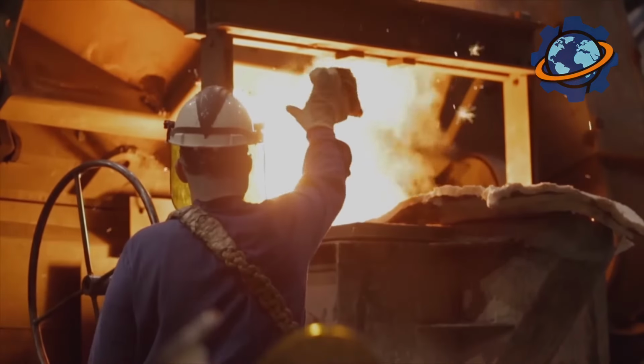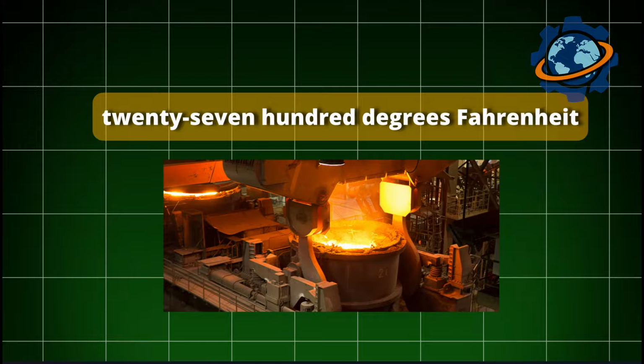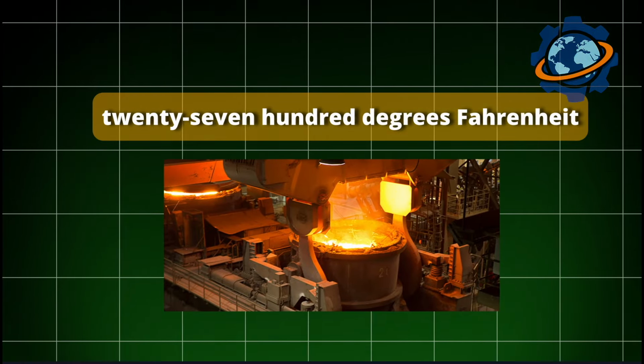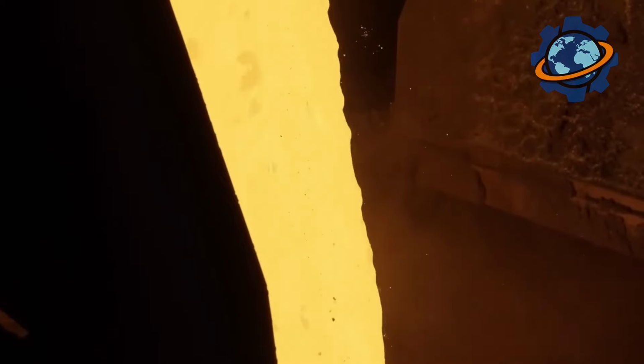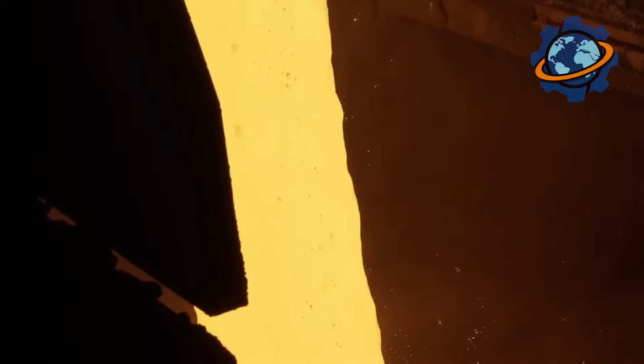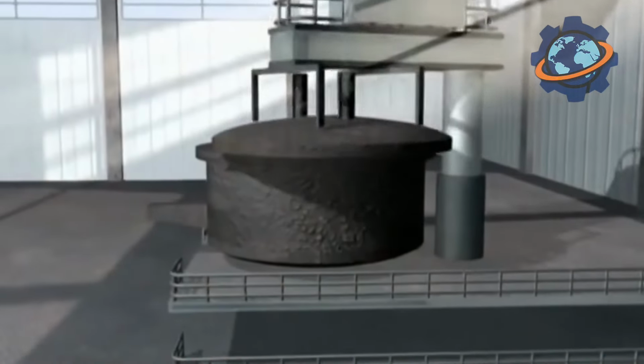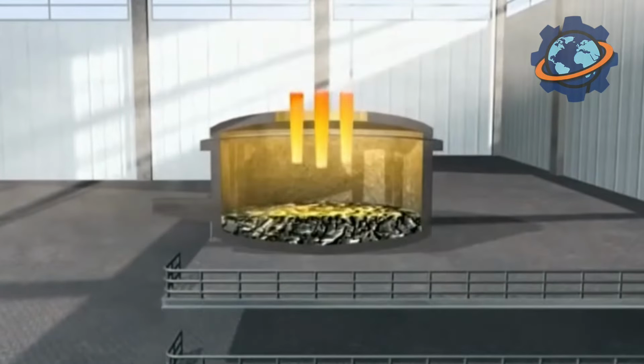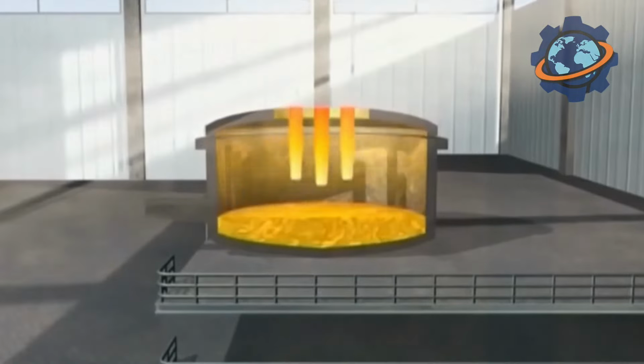Drops of molten metal flow down. At the furnace bottom, molten pig iron accumulates, an iron alloy with 4% carbon, at a temperature of 2,700 degrees Fahrenheit. It glows blindingly white with an orange tint. Pig iron is denser than slag, so it stays at the bottom, while slag, molten impurities and fluxes, floats on top.